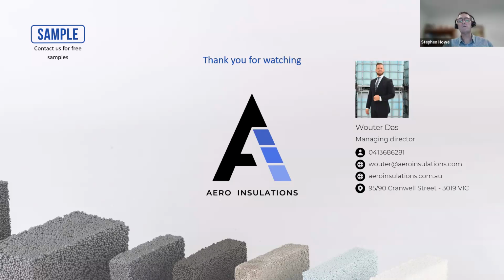And I can see that you're keen on sourcing local cements as part of the whole Australian made. Absolutely. What consideration have you made for even better CO2 savings through greener cements, or do you need ordinary Portland cement to make it work? When it comes to insulating screeds, if you want to get a really high insulating material, like you've seen in the video, we need a CEM I. So we can't really go around using anything to do with an LC3 or anything with tailings. But if it's a void filler, we can definitely use the new types of cements that are coming out with fly ash and with the tailings that are inside. Definitely. If anything, that will only aid the structural integrity of the product. Yep. Cool. Thank you, Stephen.